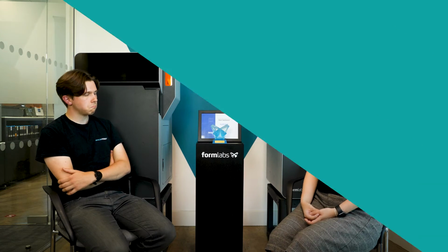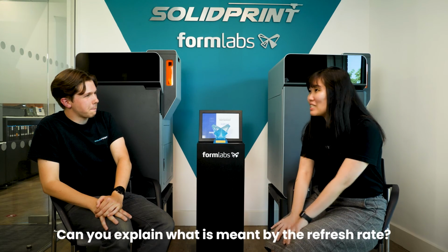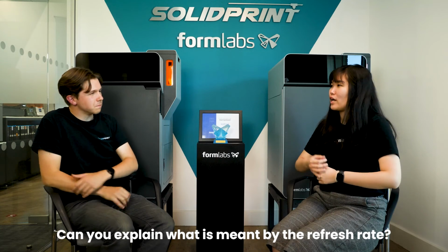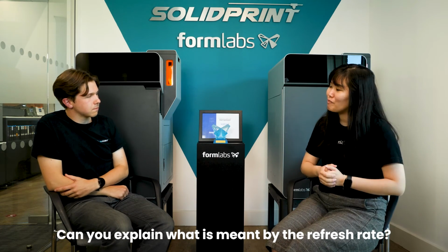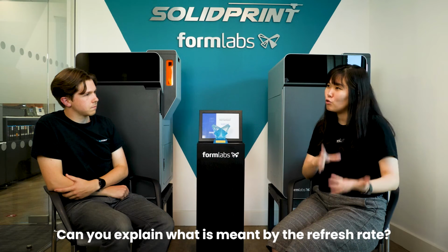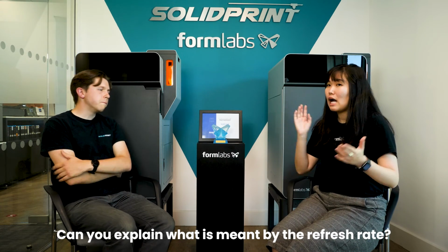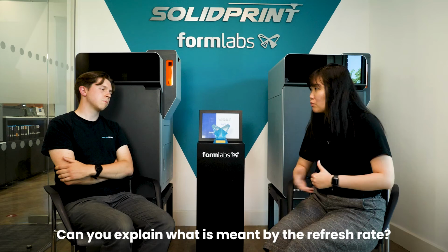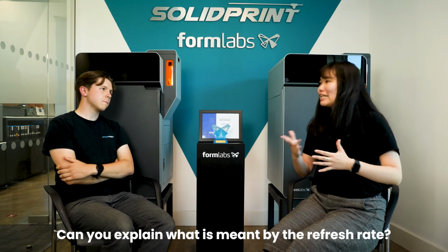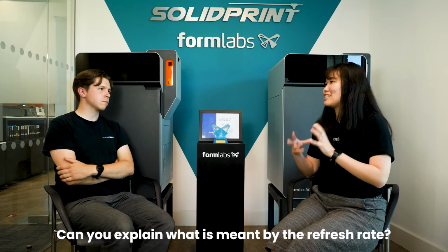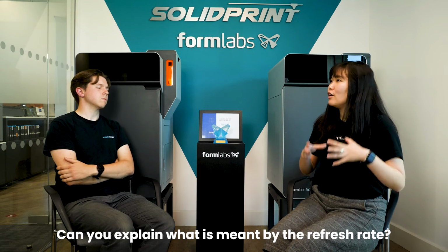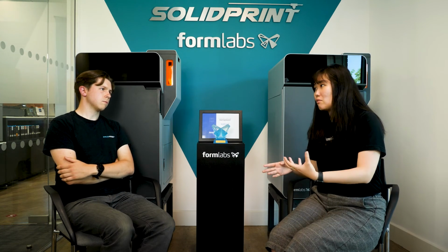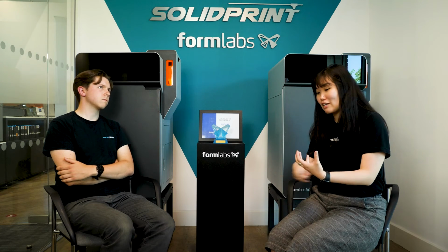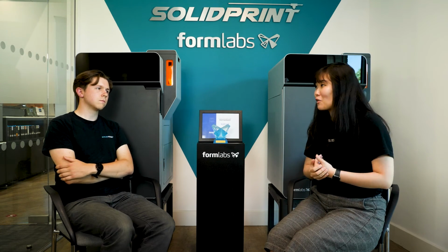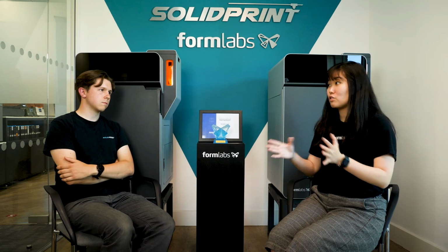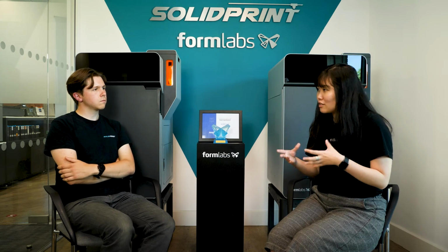Okay. Yeah. So refresh rate, essentially when you are printing with SLS, you can reclaim powder that hasn't been sintered. And then you also have to mix in new powder when you use that reclaimed powder, if that makes any sense. However, the reclaimed powder has gone through some sort of process where it's been heated up, cooled down. It's not the same quality as it was when it was brand new. So when you want to start a next print with the reclaimed powder, there's a percentage of new powder that you have to blend in to the reclaimed powder to maintain that mechanical property and, of course, a smooth surface finish. That's what refresh rate is.